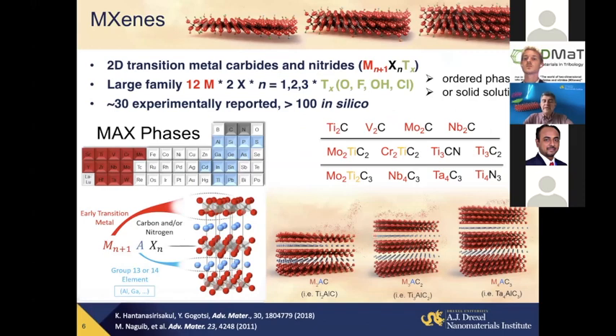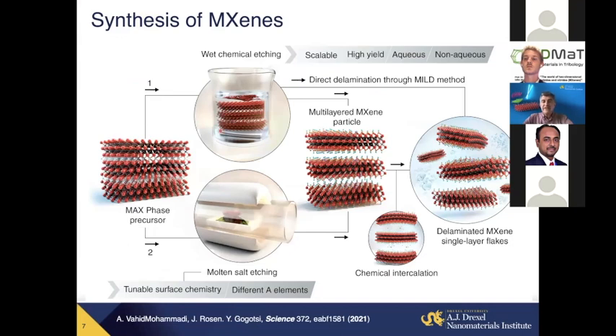bonded by a strong chemical bond, the A layer to M here, a covalent or metal bond. So we cannot simply shear them. We cannot simply use MAX phases as solid lubricants, unlike dichalcogenides or graphite would be used here. However, after we have etched it, either wet chemically or in molten salts, they all give different terminations. For example, molten salt etching will give chlorine, bromine, other halogen terminations. Etching in aqueous solution will provide OH, fluorine, oxygen here.